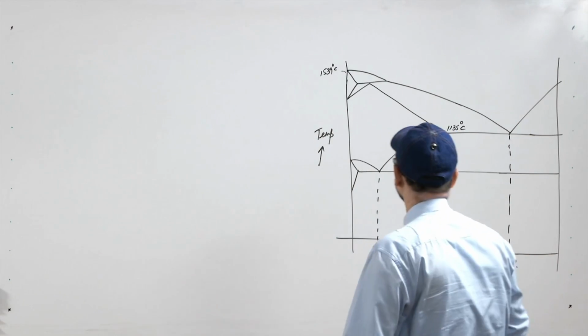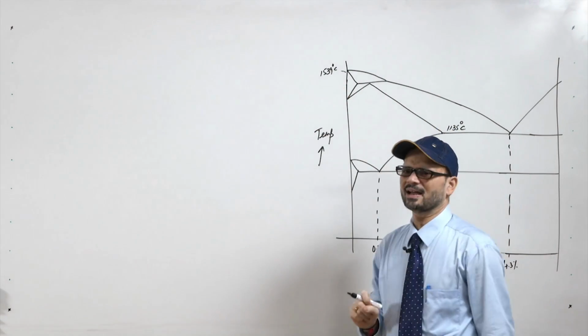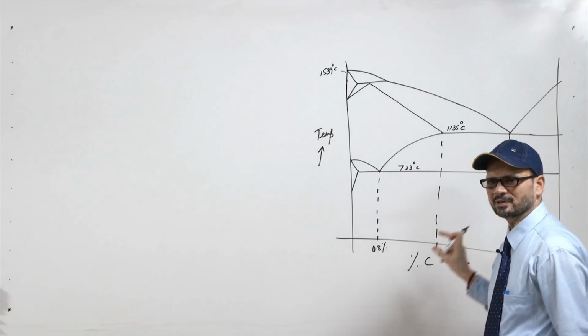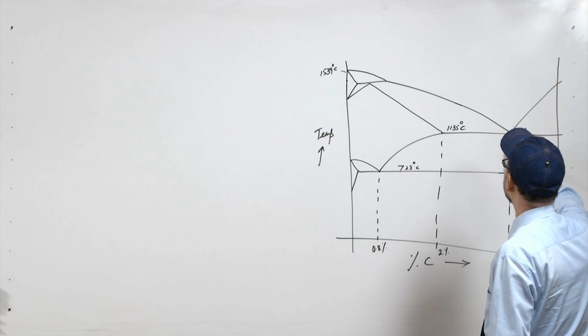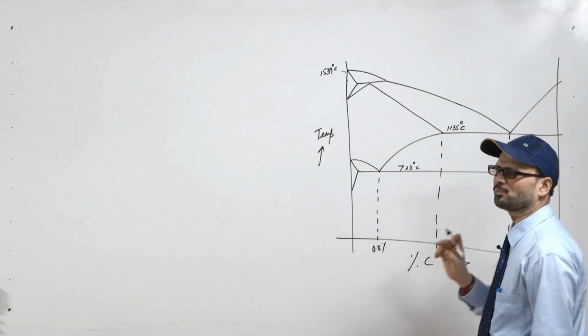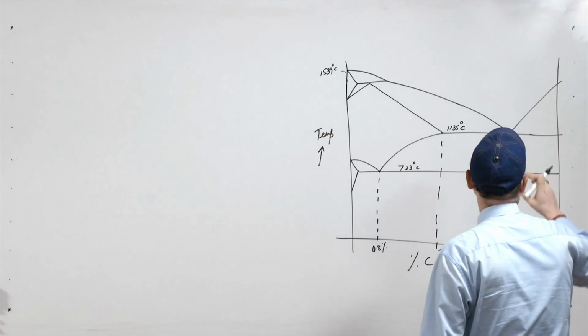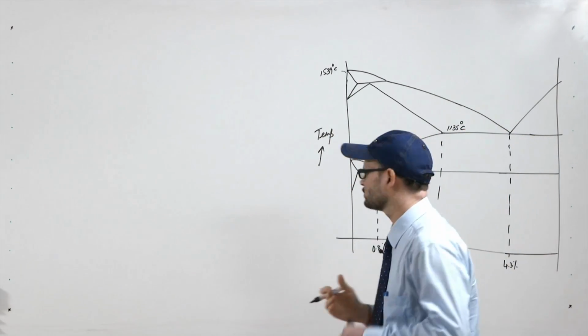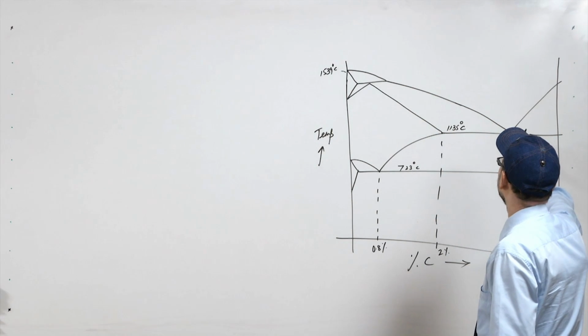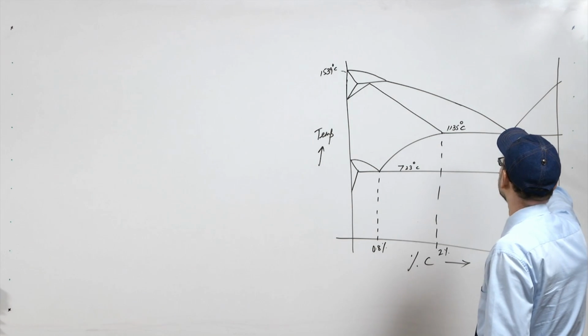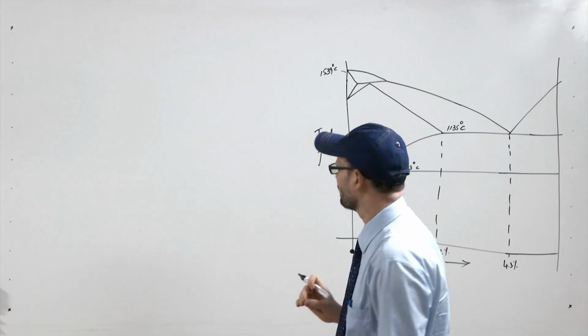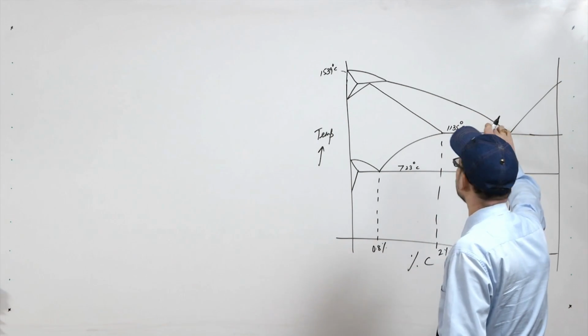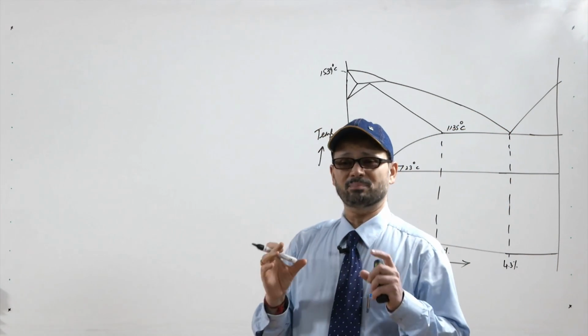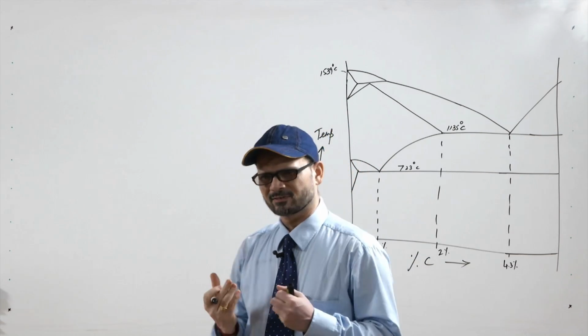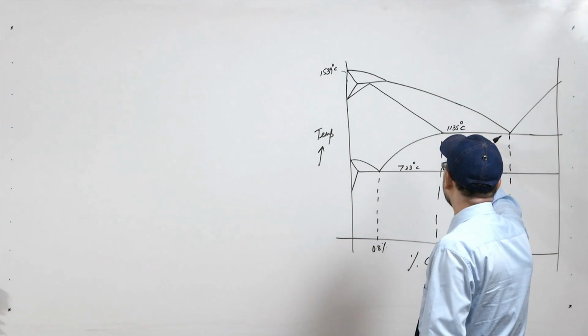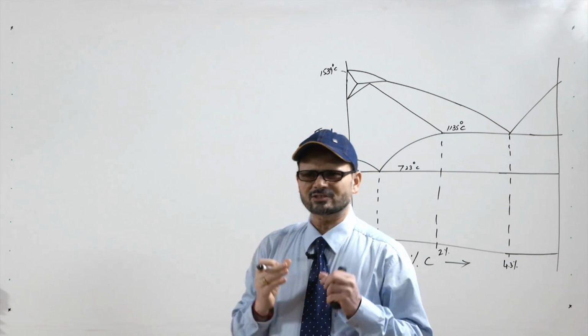Pure iron melts at about 1539 degree centigrade, but once we alloy it with carbon, the melting happens again at a single point, like the melting or solidification of pure metals. This is known as the eutectic point, where solidification finishes at a temperature of 1135 or 1137 degree centigrade. So, the castability is improved in the sense that the temperature requirement for melting is less. That is why even a cupola is enough to produce grey cast iron or cast iron varieties of materials.